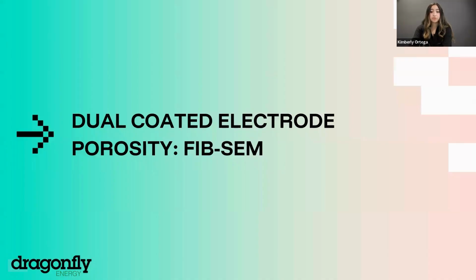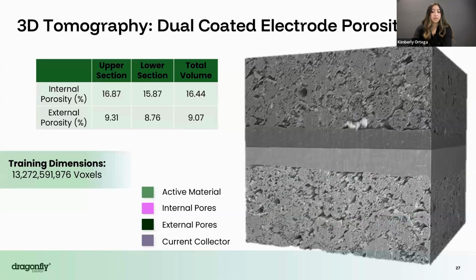So because of that, we moved to 3D tomography using the TESCAN FIB-SEM Amber X. This method uses slicing and imaging to build a volumetric dataset of the electrode microstructure. So compared to the cross-section, it's a more time-intensive process, but the semi-automated workflow makes it more manageable. It also gives us statistically meaningful data and more accurate internal versus external porosity classification. Most importantly, we no longer see delamination at the current collector, so this confirms our earlier assumption that it was a sample preparation artifact and not an electrode defect.